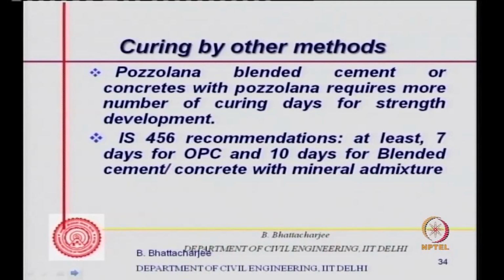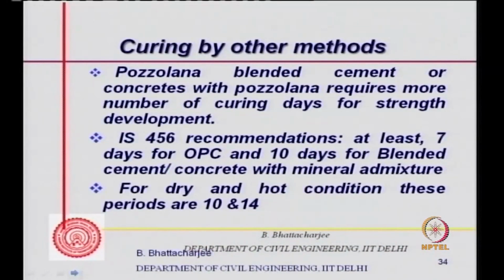So that's what I was saying, IS 456 recommendation: at least 7 days for OPC, 10 days for blended cement, concrete with mineral admixtures in normal condition. But for dry and hot condition, these periods are 10 and 14.